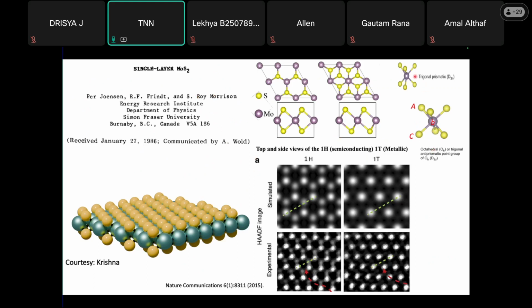Now, when you go to the monolayer system and look at just one single layer, the arrangement of atoms is like this. This is a molybdenum layer, and as I mentioned, the yellow ones are the chalcogen layers. In the most stable form, the top layer of chalcogen sits exactly on top of the chalcogen layer below, and in the middle there is of course the molybdenum layer. So this is a trigonal prismatic geometry with D3h symmetry.